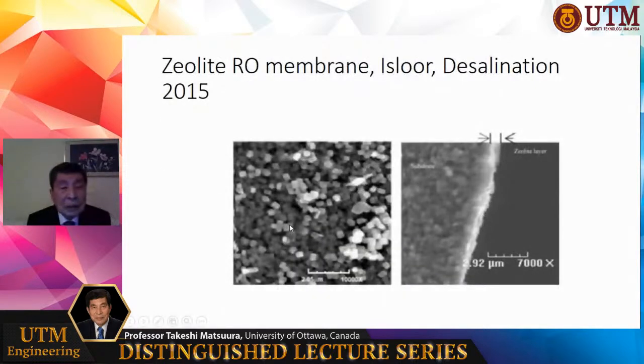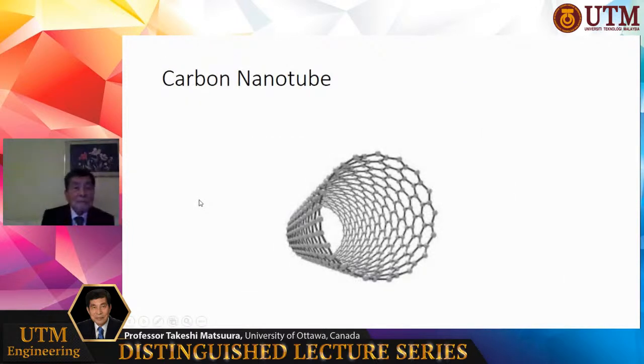This is, again, a SEM picture of the membrane. To the top polyamide surface, zeolite was incorporated. And it was done in 2015. And by this incorporation, the productivity, the flux of the membrane could be increased quite a lot. Another thing, this is a very popular subject nowadays, it is carbon nanotube. You have heard many times about this material.